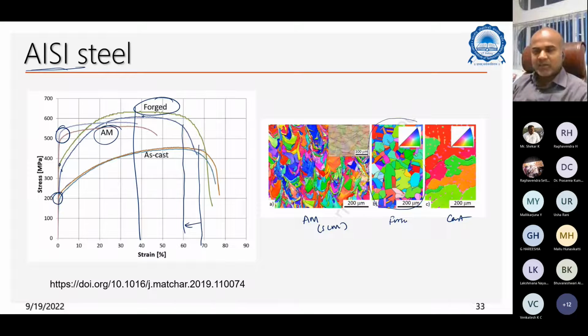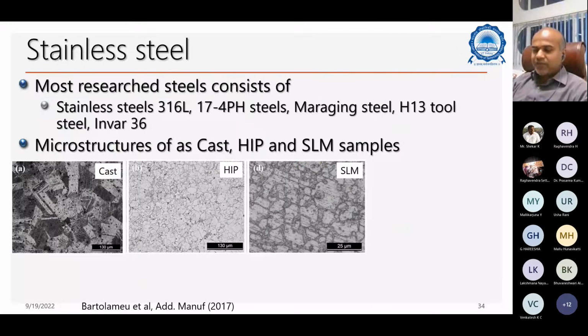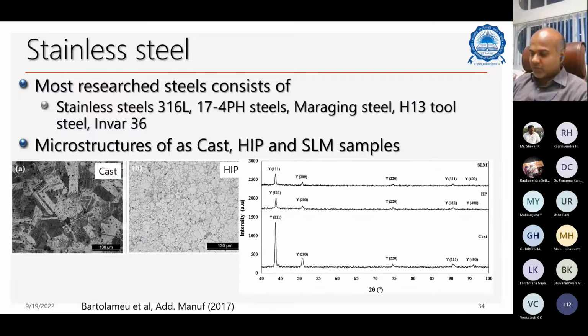I think additively manufactured alloys will do a much better job than the as-cast or forged ones, because in the microstructure you see slight strain hardening behavior here, which you don't see in the AM alloy. This is 17-4 PH steel, as I told you. So you're talking about three comparisons here.